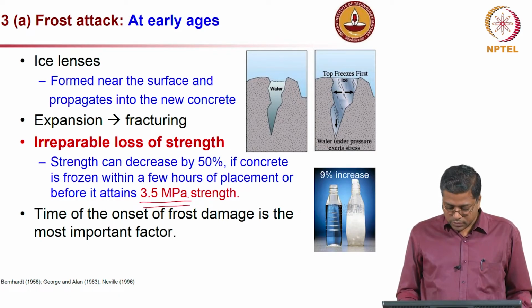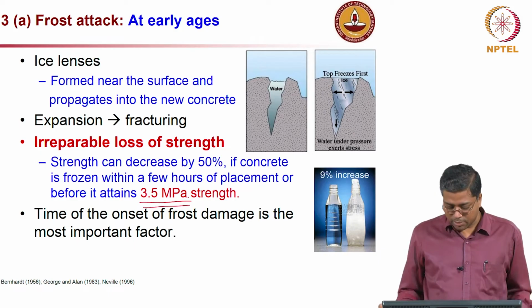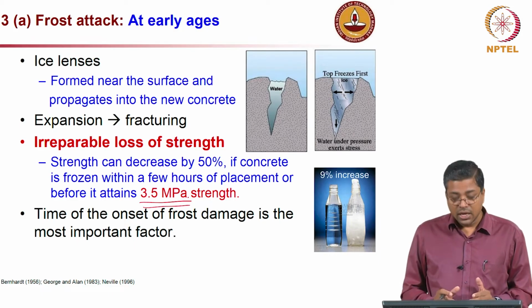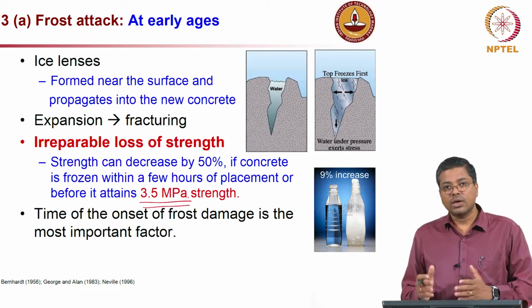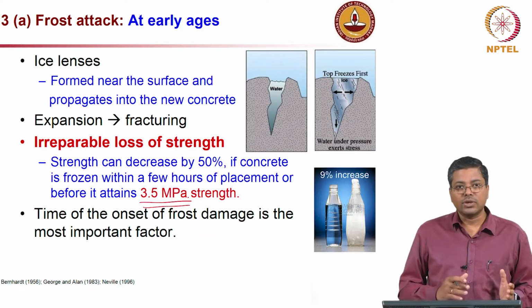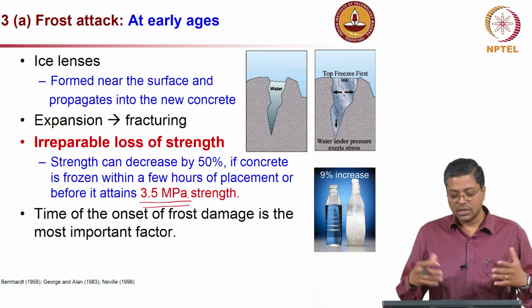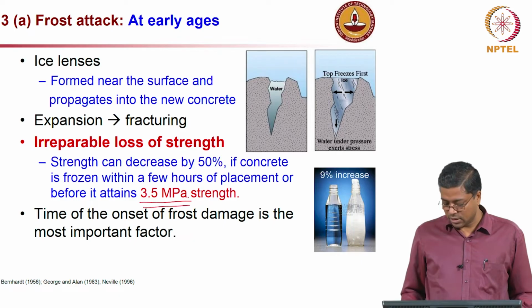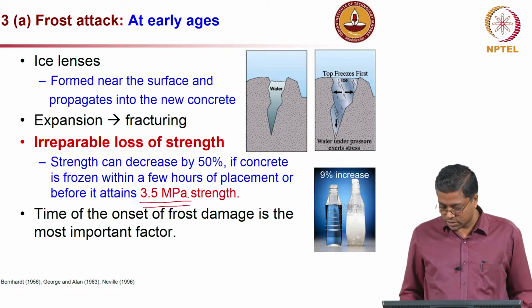Now, the time of the onset of frost damage is also most important. That means, if the frost damage happens after 3.5 MPa strength is attained, then we can still manage to get sufficient strength later.